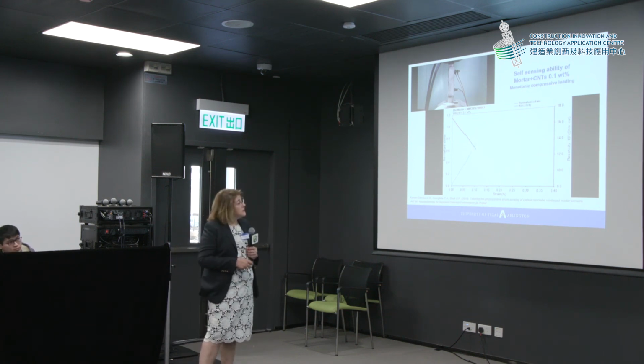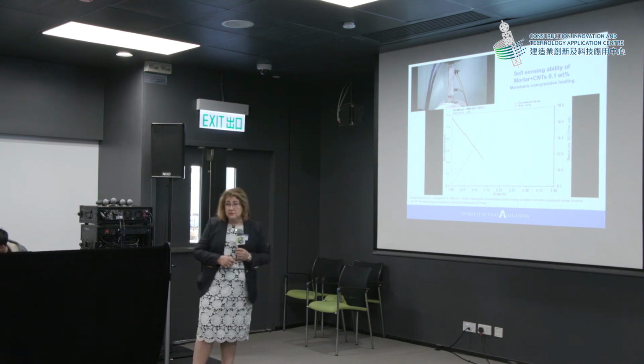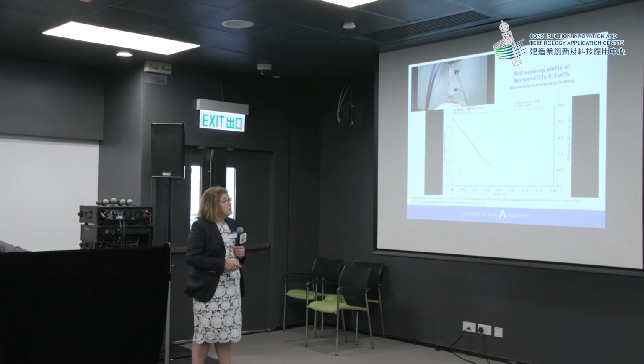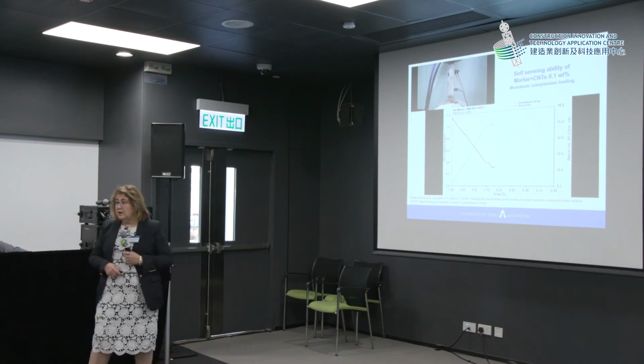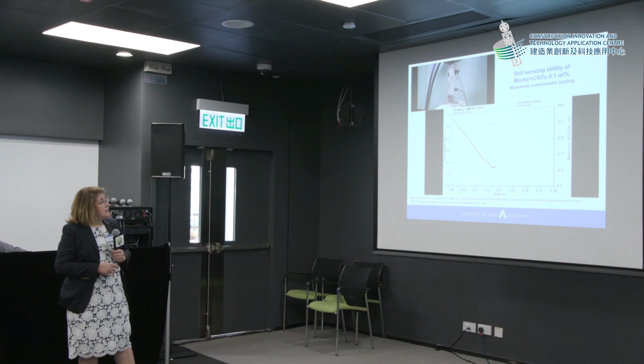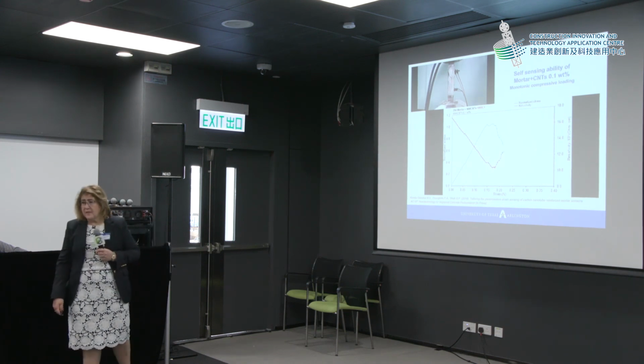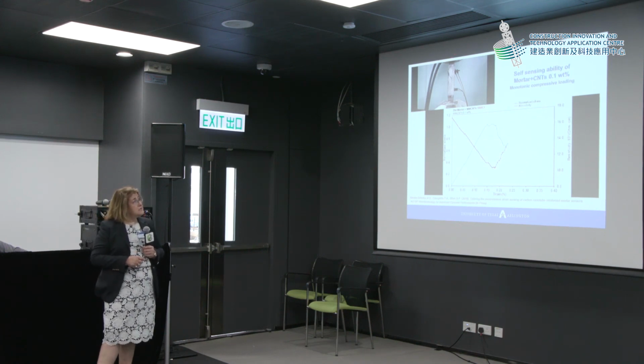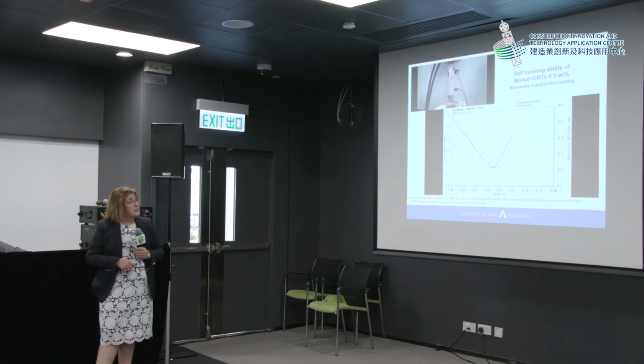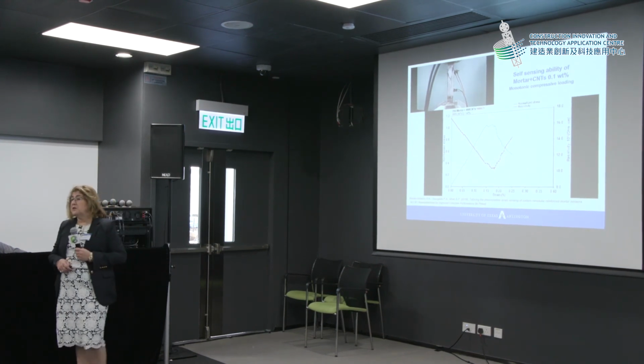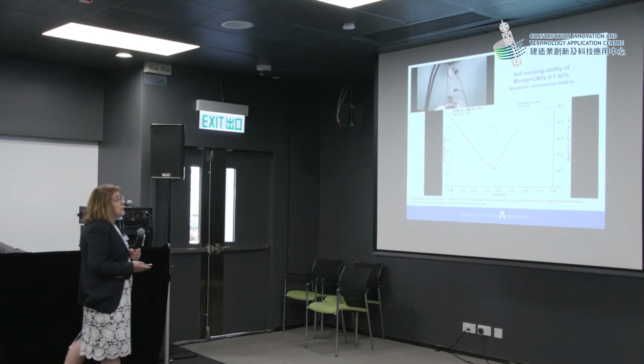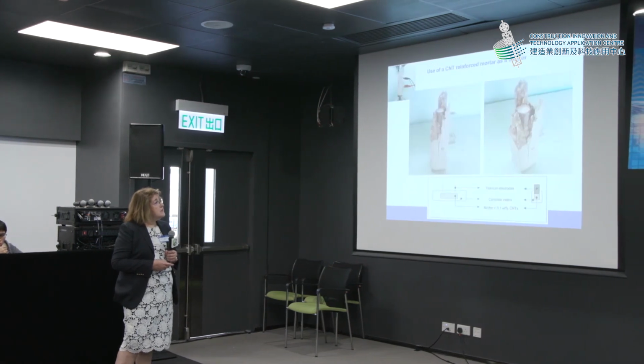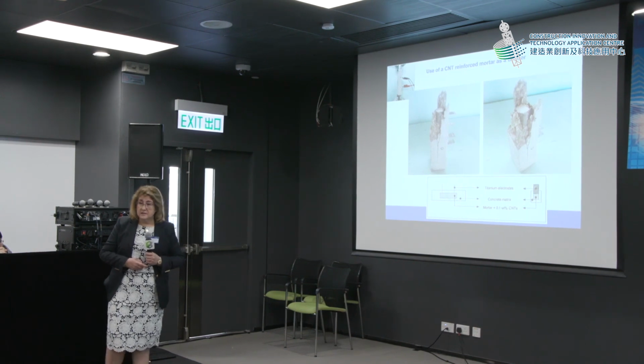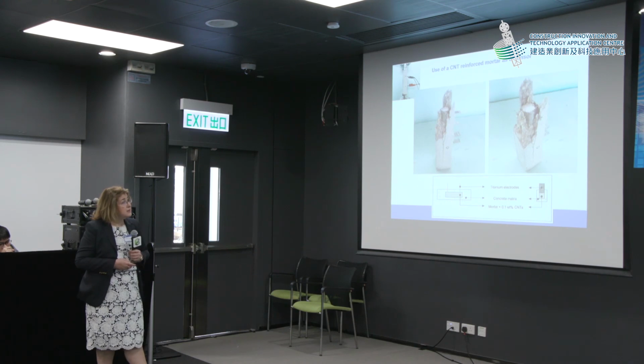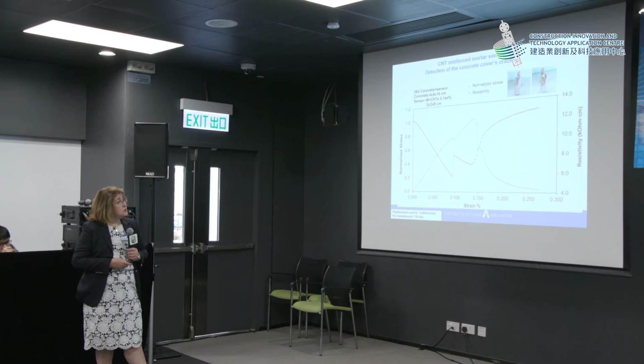What I'm showing to you here is two curves. One is the stress-strain curve. The blue is the stress-strain curve. And the red curve is the piezoresistivity curve, as we call it. And the piezoresistivity curve, you can see how the specimen here fails along its loading. And this is mortar. We have the same exact curves in concrete. And look at the two curves, they are like mirror image curves. We can discuss this later if you want, because we do have nice results. We can use the same mortars as sensors inside concrete elements, structural elements, and we do have the exact same results as I'm showing here.